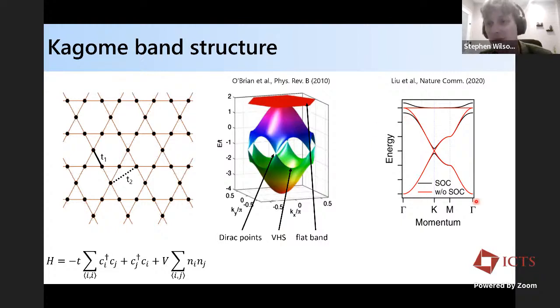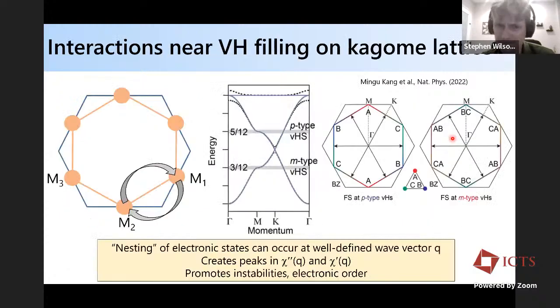And so here on the right, you can just see these high symmetry cuts across these features. And you can see here, there are these two saddle points, which are inequivalent, meaning that one of them, for instance, is a so-called p-type or pure type Van Hove singularity, where at that M point the electronic wave function is derived from a single sublattice amongst the three sublattice Kagome net, whereas the lower Van Hove singularity is the m-type or mixed type, where you can have a mixture of electronic wave functions from two different sublattices in the Kagome net.